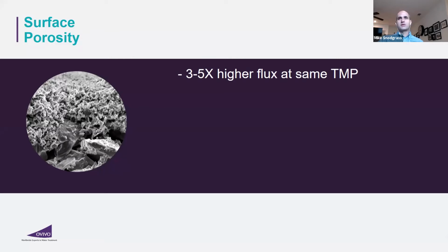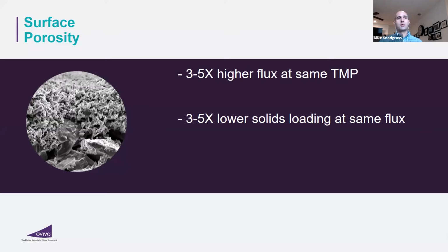So SiC is probably the most porous membrane out there, with about 50% surface porosity. Because of that, we can achieve about 3 to 5 times the flux rate at the same TMP compared to other membranes. Also, the higher surface porosity reduces your fouling. When you think about it on an individual pore level, and think about solids trying to bombard that pore as water's passing through, if you have a lot more pores, then there are certainly going to be a lot fewer solids hitting the pore surface. So it definitely lowers your fouling rate significantly.